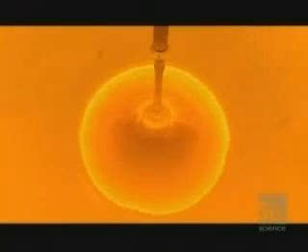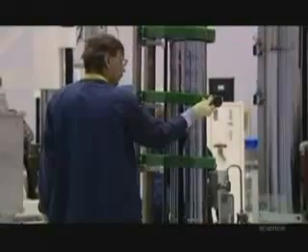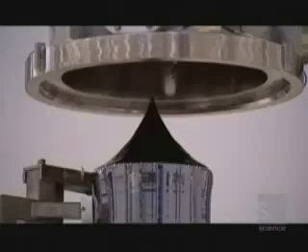As the molten polysilicon is allowed to cool, the seed crystal is slowly withdrawn at around 1.5 millimeters a minute. The result is a single silicon crystal weighing around 440 pounds and with a diameter of around 200 millimeters. The crystal is so strong its entire weight can be supported by a single thread just 3 millimeters across. But it is brittle, and it must now be cut down to size without shattering.